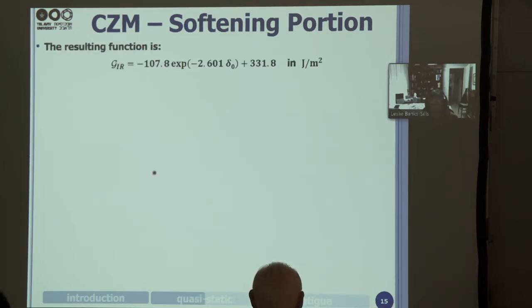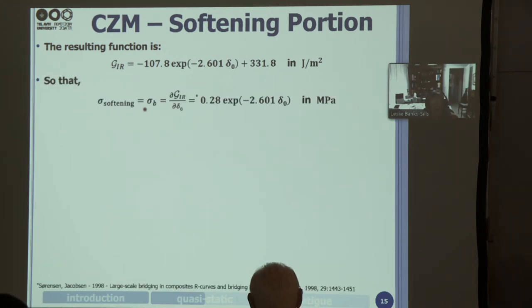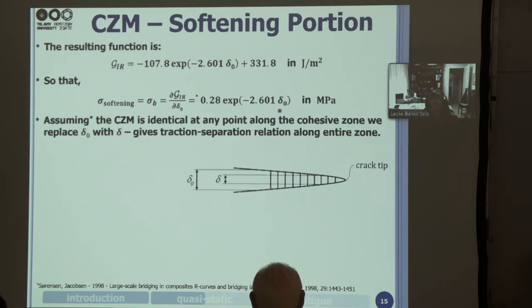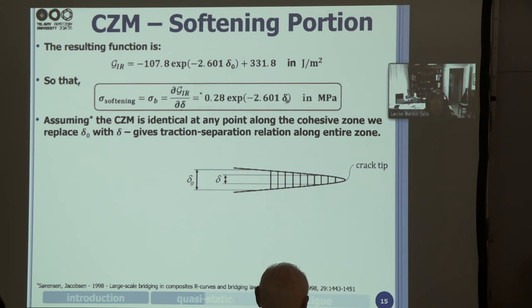So now we're going to have to make an assumption. This is our G1R curve with respect to delta zero, the opening at the initial tip of the delamination. And we can get the softening part from the literature by Sorensen and Jacobson. If you differentiate G1R with respect to delta zero, we can get the sigma B, the softening part of the traction separation law. They make an assumption, and we made the same assumption, that we can use this expression for G1R and replace delta naught by delta.